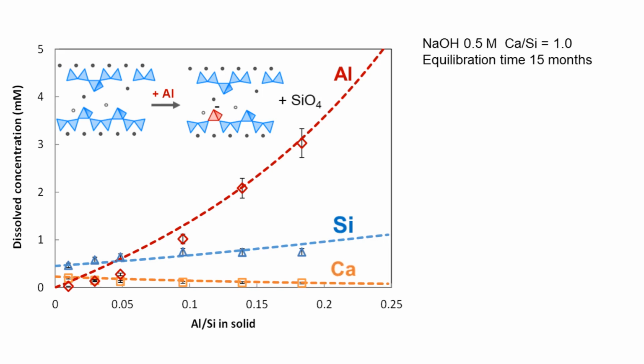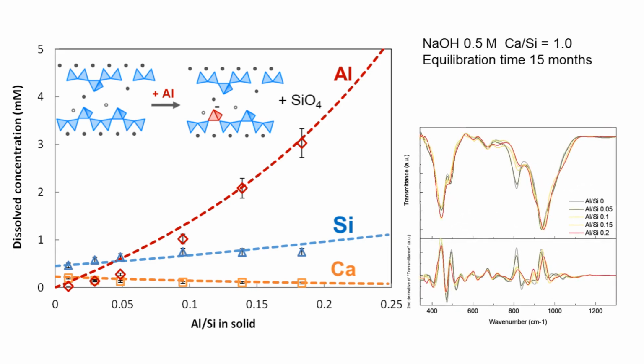Why does that happen? This is due to the growth of calcium oxide sheet along the silica chain. So with more aluminum in the system, the silicate main chain length would increase. And this is confirmed by the FTIR results, as we see the decrease of Q1 signals.